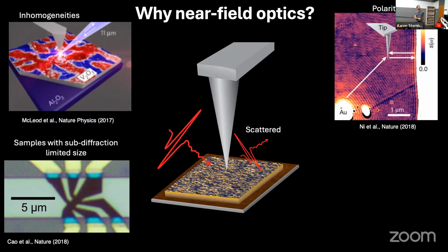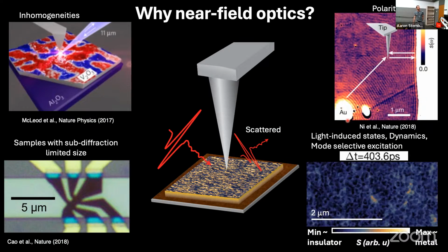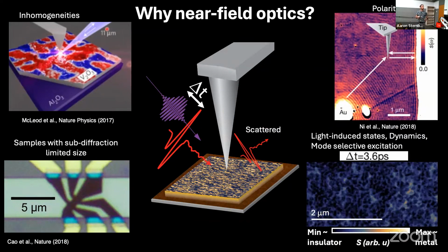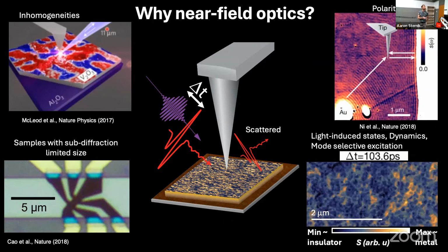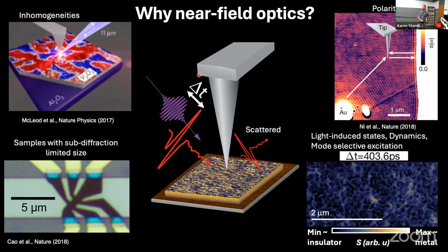First, this gives you a way to confine light to the nanoscale and play with subdiffraction limited photonics, but these modes also give you direct information about the properties of the material. This is a probe, in a sense, of the dielectric tensor of the material that hosts these waves. And finally, when we use pulses of light, we can come in with a pump to change the state of a material, and then come in with a probe at a variable time delay in order to directly resolve how the system evolves from one state to another in real space and in real time.